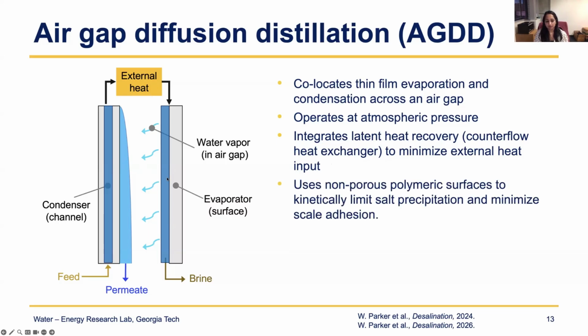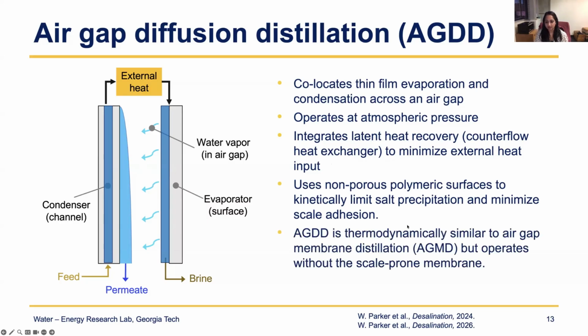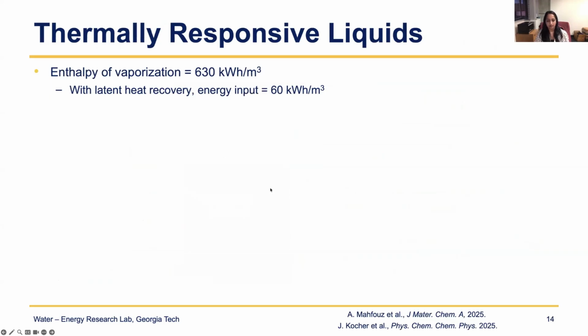It's entirely made out of plastic surfaces, polymeric surfaces with very low surface energy, and so corrosion is not an issue, and you also have very low scaling because of the low surface energy. So no membranes, no metallic heat exchangers, just plastic surfaces with heat recovery integrated.